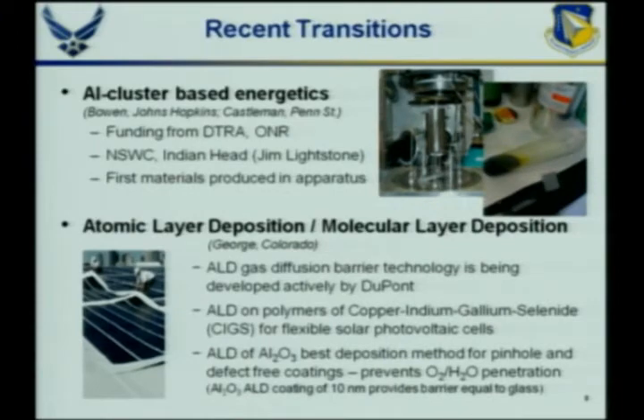Another area that we've been able to transition is some applications of atomic layer deposition. We've been working in this area for quite a while. You see it pop up in other programs frequently these days, but Steve George at the University of Colorado has pioneered a lot of this work in this program. Atomic layer deposition gives you the capability to put down conformal coatings and control them one atomic layer at a time. So you can really control the thickness, and they're also very defect-free, so you can make very nice solid coatings. This application is being pursued by DuPont on flexible solar cells, where the coating is used to prevent oxygen and water penetration, so it's a gas barrier. A coating that's 10 nanometers thick provides as much protection as a large piece of glass does.